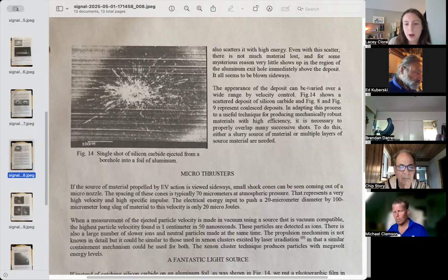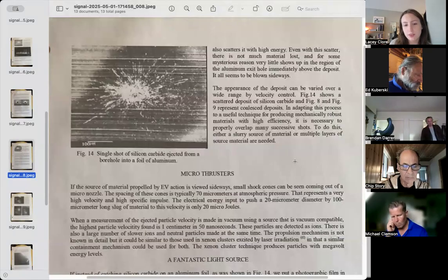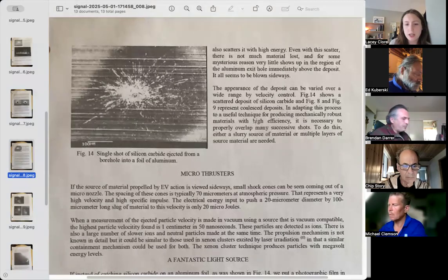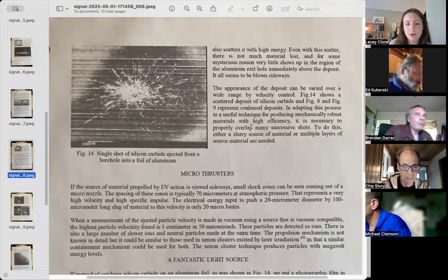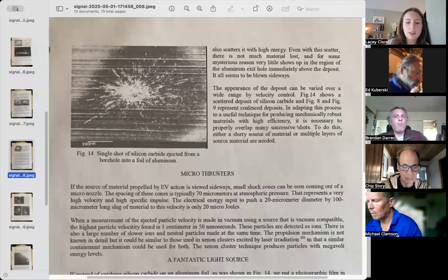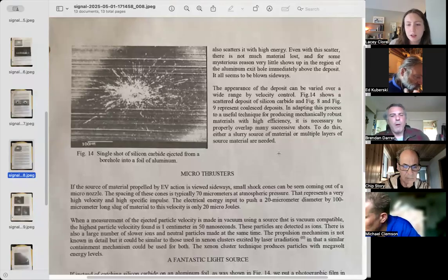The appearance of the deposit can be varied over a wide range by velocity control. Figure 14 shows a scattered deposit of silicon carbide, and Figure 8 and Figure 9 represent coalesced deposits. In adapting this process to a useful technique for producing mechanically robust materials with high efficiency, it is necessary to properly overlap many successive shots. To do this, either a slurry source of material or multiple layers of source material are needed.